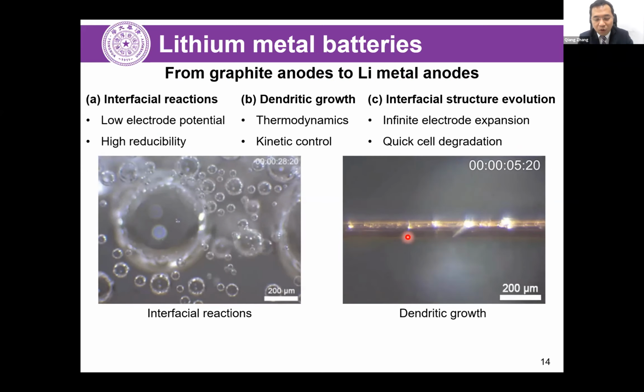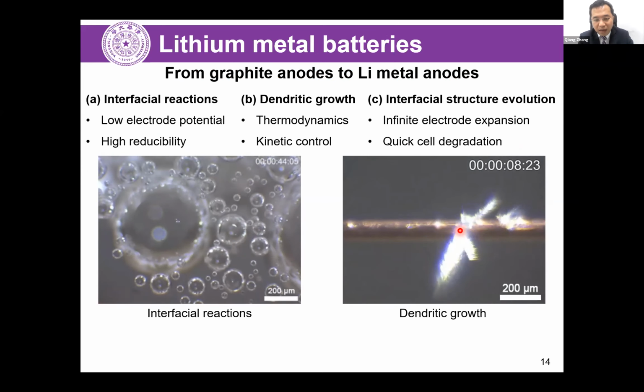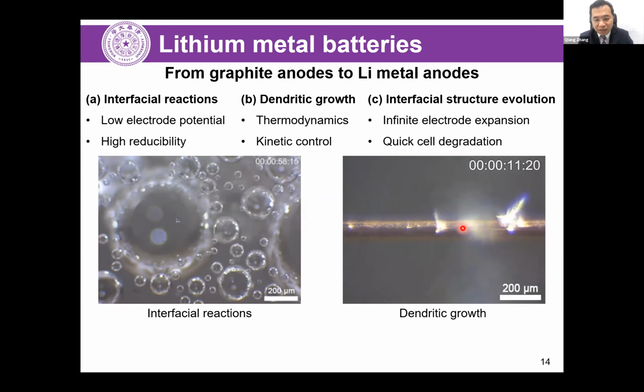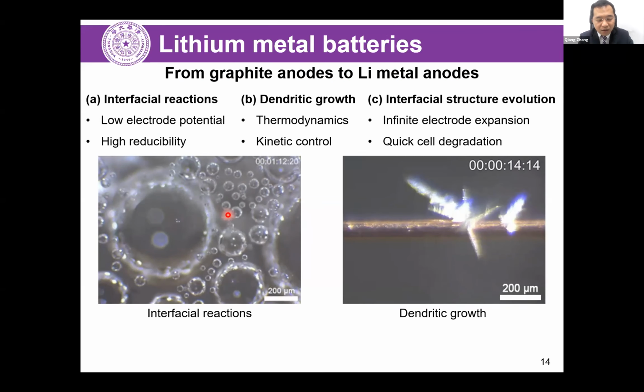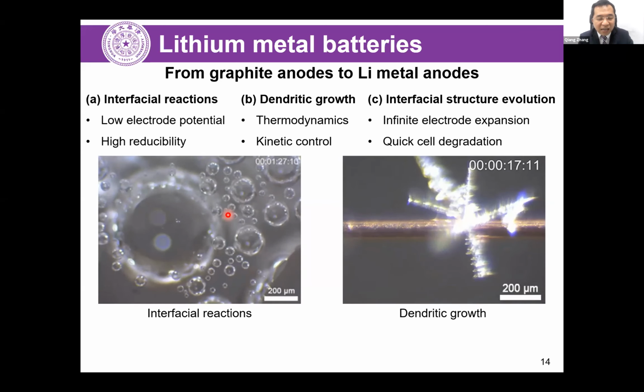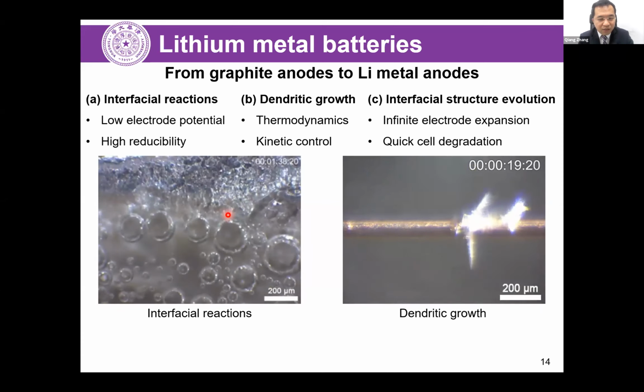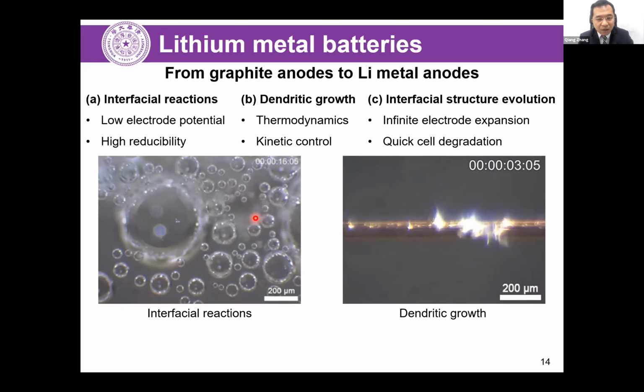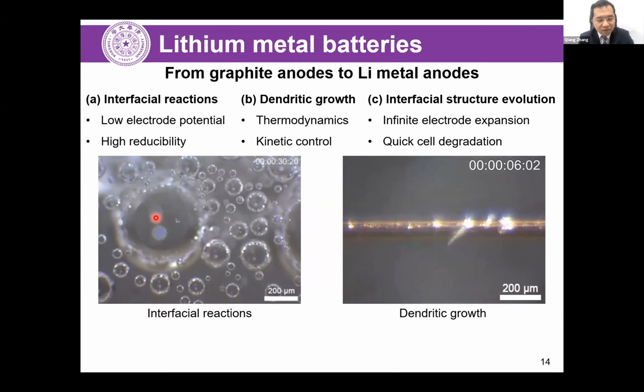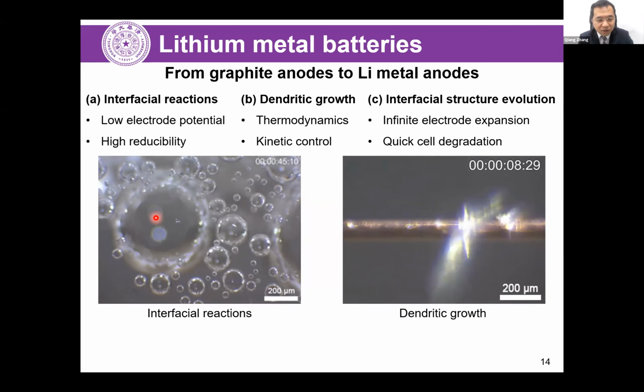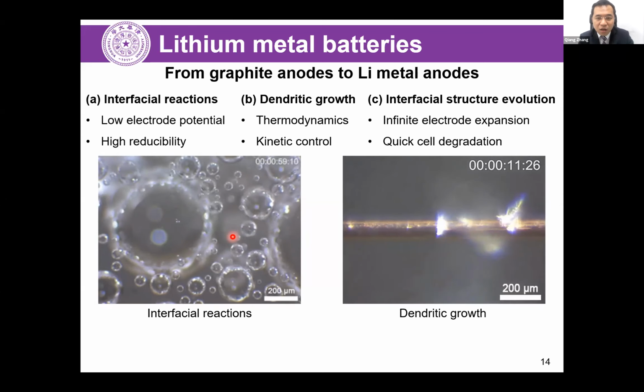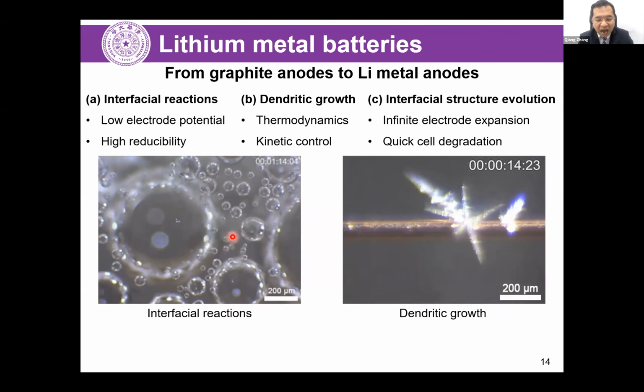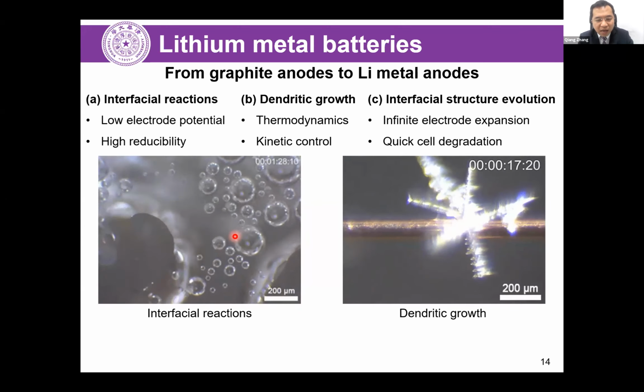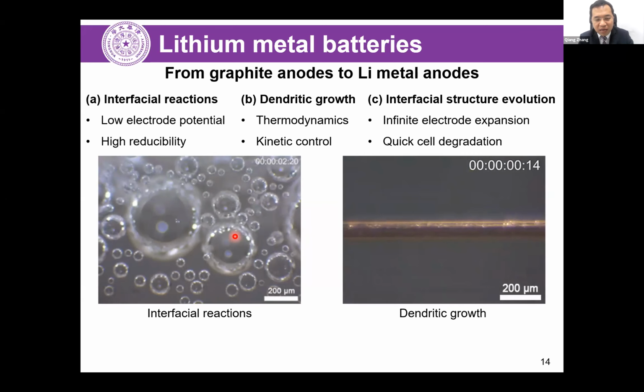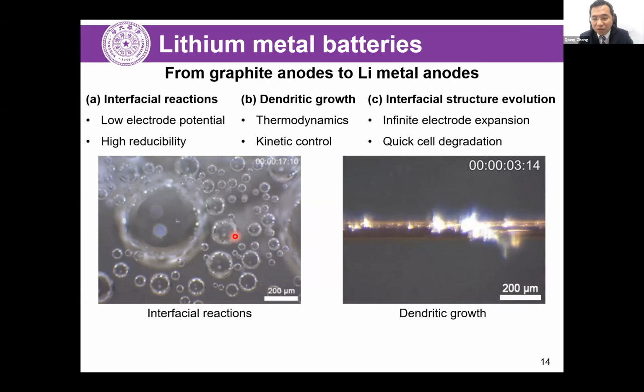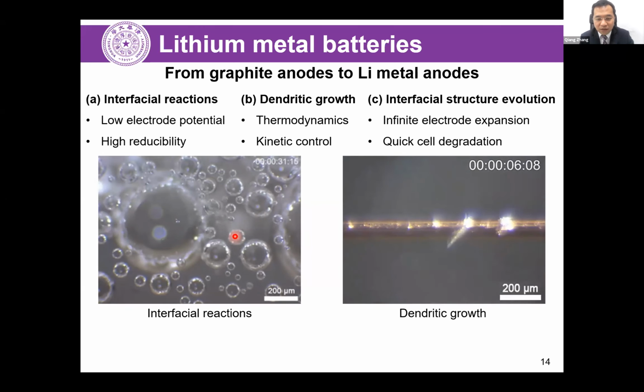Some dendrites will form on the surface, and the dendrites can penetrate through the separator and introduce safety issues. While the highly active lithium metal anode will touch the electrolyte and introduce some side reactions, which produce a lot of gas and some solid byproducts. In fact, the gas products include hydrogen, methane, ethylene. They are quite dangerous. So in this case, if we pursue a high energy density battery, it is found that the chemistry happening at the interface between the metal anode and the electrolyte is quite challenging.